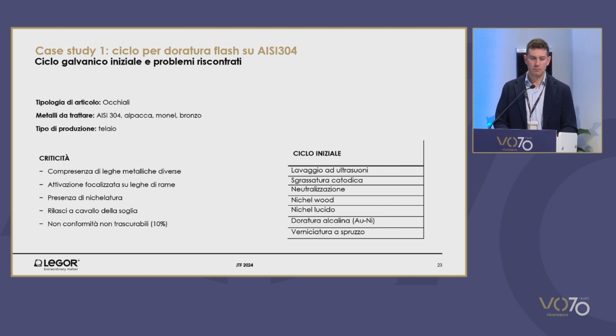This is why subsequent studies were carried out within LEGOR to develop nickel-free electrodeposition cycles whose objective was that of reducing the nickel release after electrodeposition. In this study, the request that had been put forward by a client in the eyewear industry was very complex. Within the same eyewear, within the same glasses, there were copper alloys and stainless steel, and basically you have to prepare the surface for that purpose.